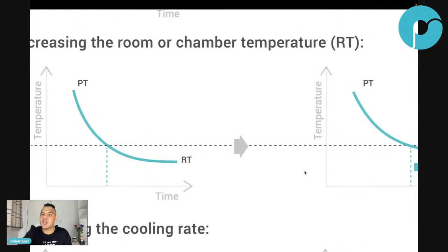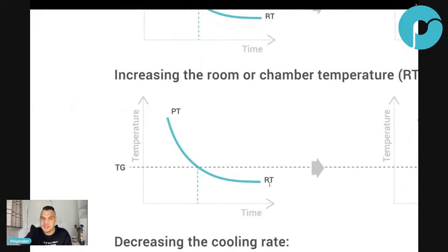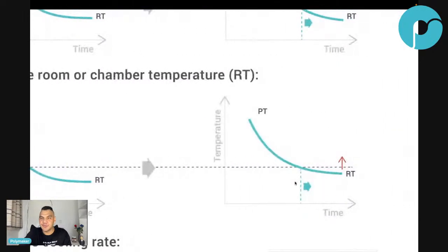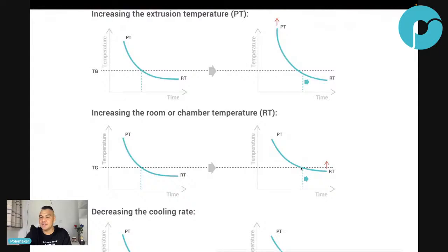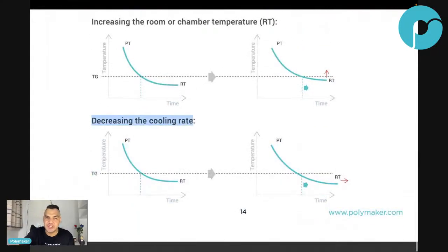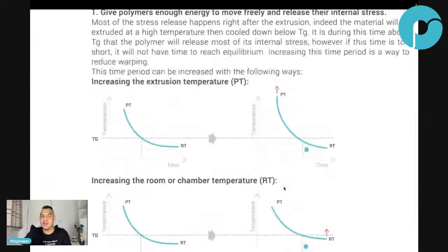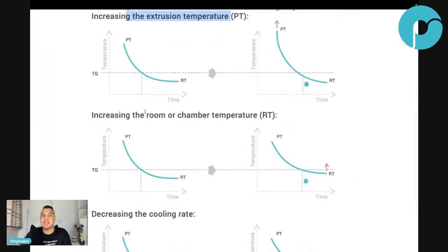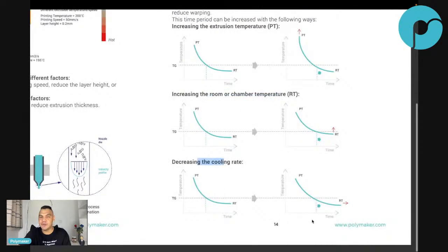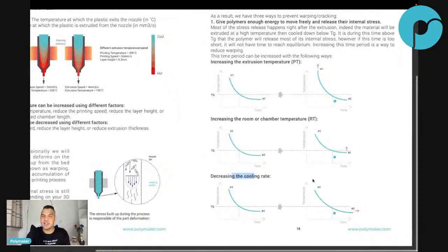So the next one is room temperature. If you increase the room temperature from here to here, then you will also increase the time. If you decrease the cooling rate, which means you don't use a fan, then it's the same. So whatever you do, increase the printing temperature, increase the room temperature, decrease the cooling rate, you are increasing the time at which the polymers stay above TG, which means you are preventing stress from accumulating, which means you are solving your warping issue.